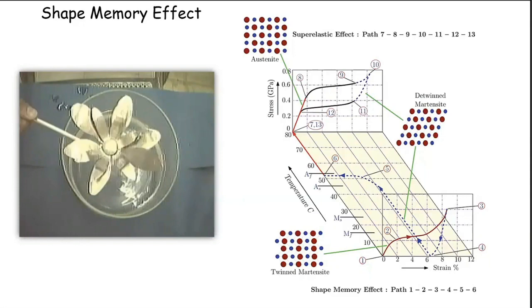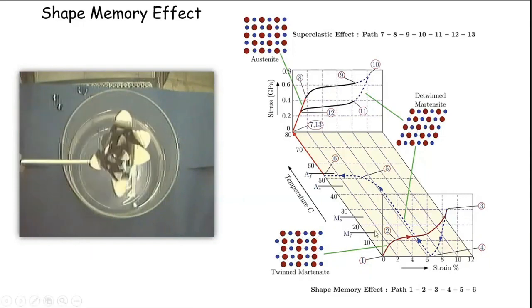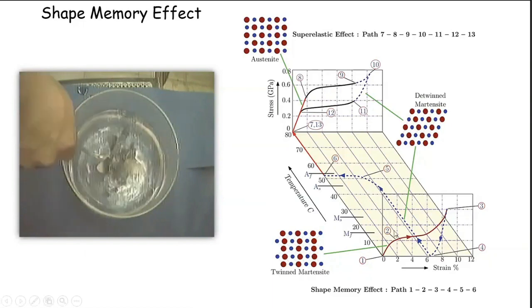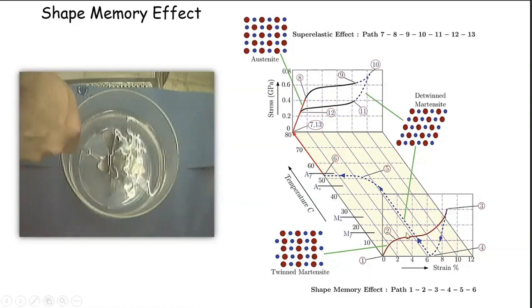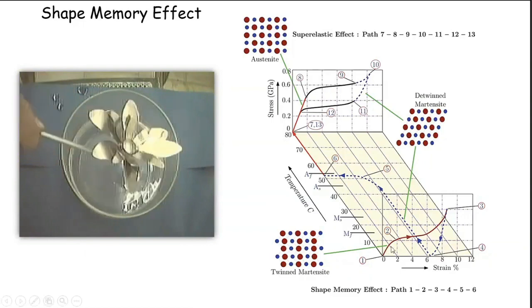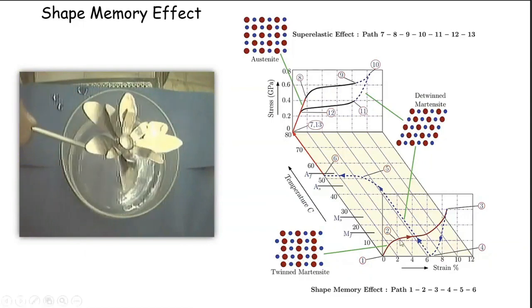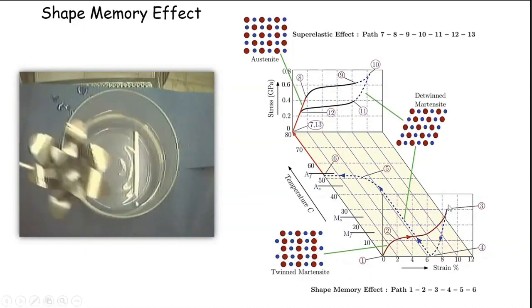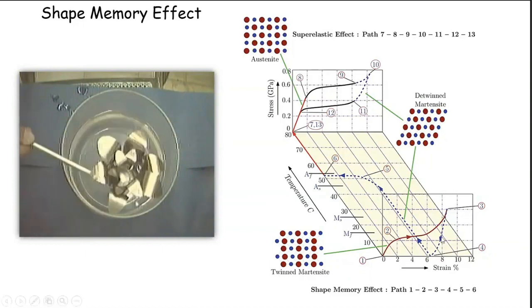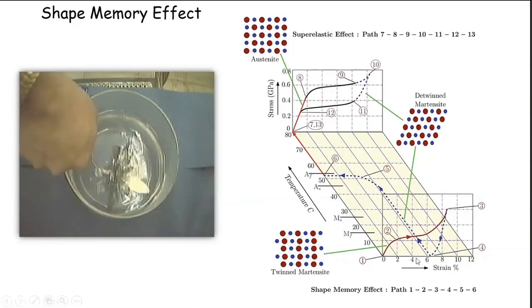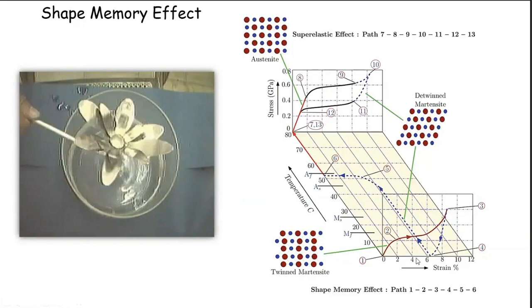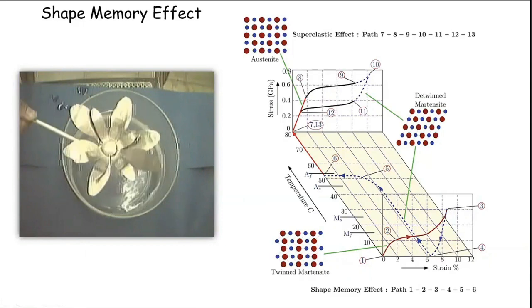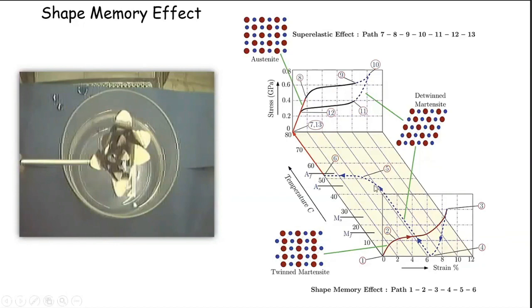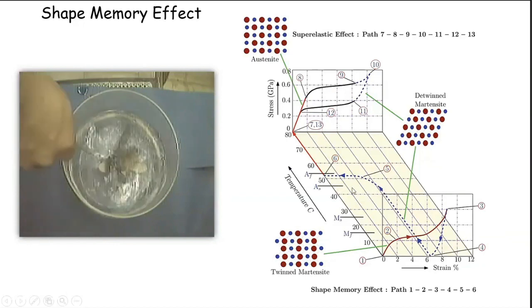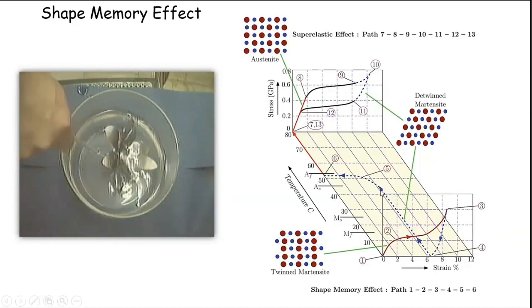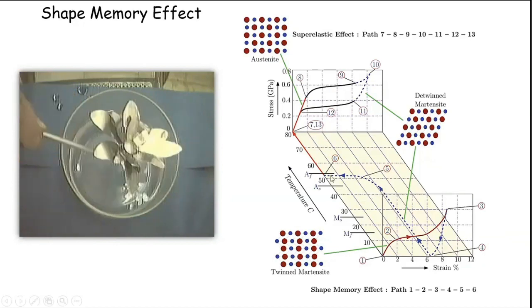So if I look at it from a material point of view, I take your attention to the figure on the right-hand side. What you see here is like a stress strain diagram. You deform the material at room temperature, and when you unload it, it remains more or less where it is. So that's the set, or the plastic deformation that you give to it. But if you heat it, at a temperature above what we'll refer to as AS, it starts recovering its original dimensions, and by about AF, it has completed that recovery of dimensions.